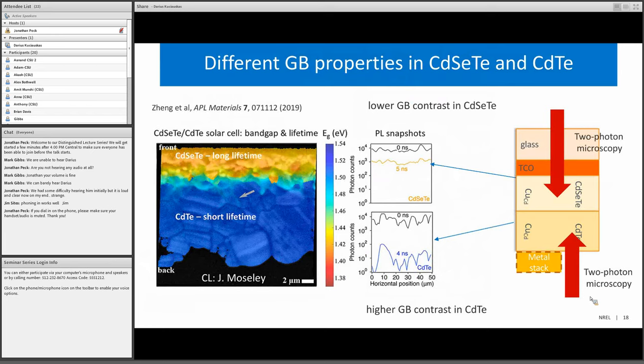Now, not all grain boundaries in cadmium telluride are bad, and not all carrier lifetimes in cadmium telluride are short. Here is a most recent example published last week, when the measurement is done on solar cells fabricated at First Solar. They are graded absorbers in which the cadmium selenium telluride is on the glass side, on the top in the cathodoluminescence image. Cadmium telluride is at the bottom at the bare contact side. And by this time, I figured out how to do these measurements through the glass, so the special transparent contacts are not needed. And the two-photon excitation microscopy data shows that the grain boundary contrast is not that high, especially for the cadmium selenium telluride part.